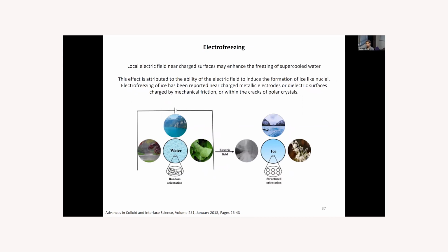So it was already shown in a few articles in the literature that the local electric field near charged surfaces can enhance the freezing of supercooled water. This effect is attributed to the ability of the electric fields to induce the formation of ice-like nuclei. Electrofreezing of ice has been reported near charged metallic electrodes or dielectric surfaces, charged by mechanical friction, for example, or within the cracks of polar crystals.